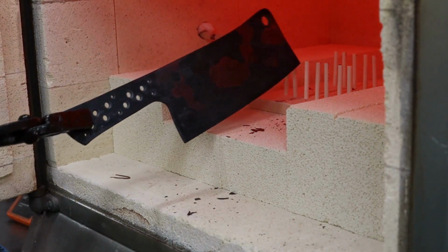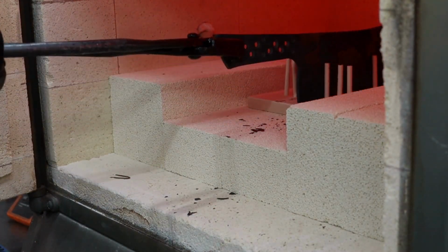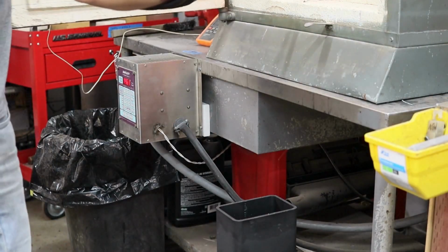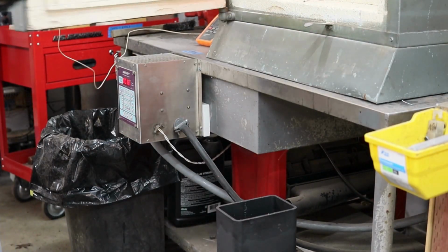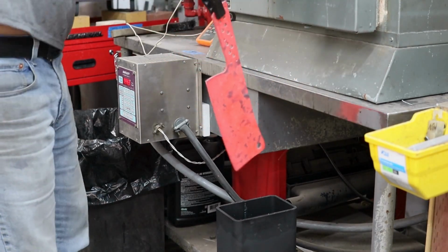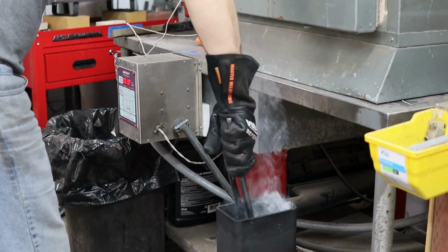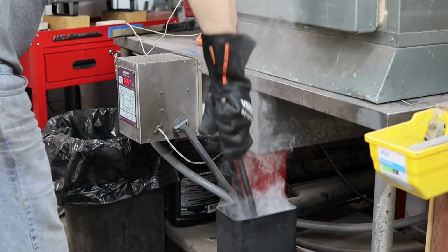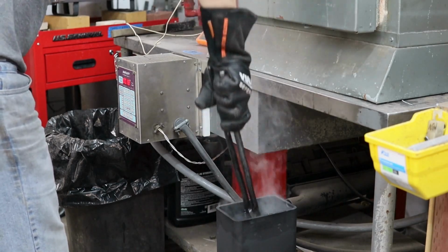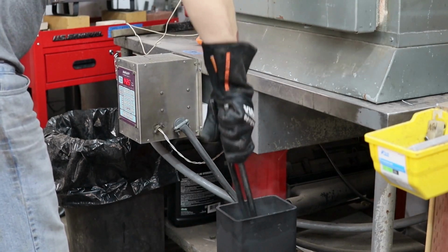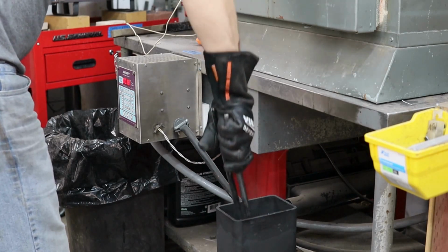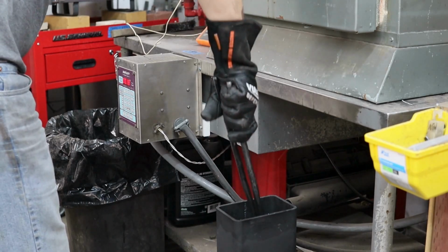I'll quench the blade at 1475 degrees Fahrenheit in Parks 50 quench oil, and I heat that quench oil to around 120 degrees before quenching. Now if you listen closely here, you can hear a loud ting during the quench, and I thought for sure I was going to find a huge crack in this blade once I pulled it out of the quench tank. You can even hear me grunt because I thought I just ruined a bunch of Damascus and forging work.